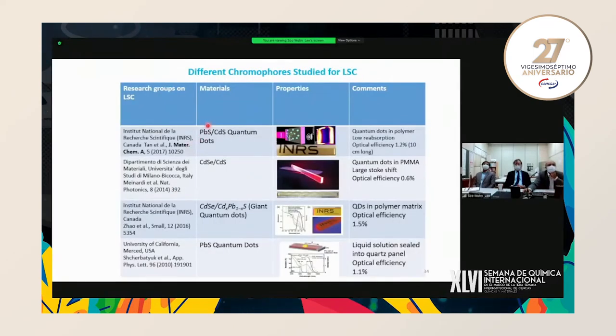Worldwide, many researchers are working on different chromophores, and some of the main researchers are from Canada, INRS, and Italy groups. They fabricate quantum dots based on lead and cadmium, so their efficiency is quite low, 1.2% optical efficiency. This is from the Italy group, cadmium selenide and cadmium sulfide. This efficiency is 0.6. The INRS group from Canada fabricated giant quantum dots based on cadmium selenide and cadmium lead sulfide, with an efficiency of 1.5. Another is lead sulfide quantum dots, fabricated by University of California, USA, with an efficiency of 1.1.